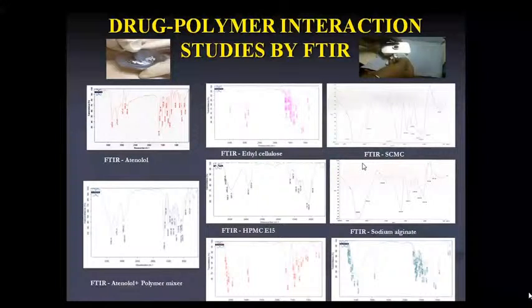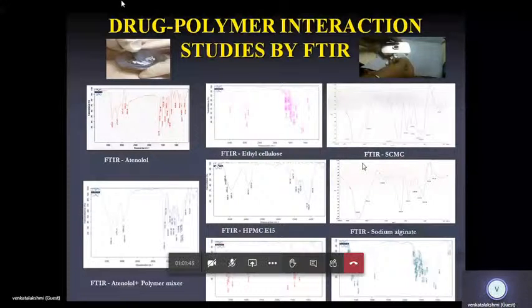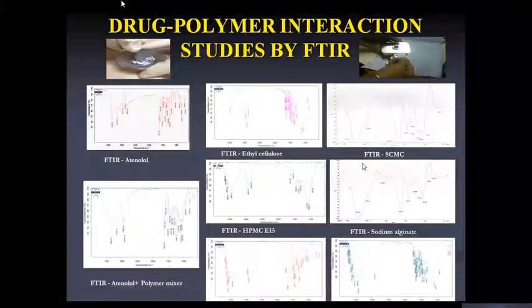Okay, if there are any interactions between the drug and polymer, how do we know? Definitely there will be changes in the peak because of the forming of a new functional group. Usually, if any interaction happens, it can form a different functional group, so that you can obtain a different peak. From that you can compare your sample with the standard sample, and you can confirm that there is no chemical interaction between your drug and polymer.